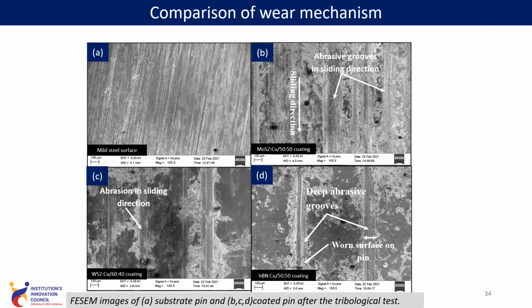This is the comparison of wear mechanism. As you can see, this is a mild steel surface. This is the MoS2 copper surface, WS2 copper surface, and hBN copper coating. In this, it is observed that abrasive grooves are formed. You can see the abrasive sliding direction. This is the surface that showed the lowest wear resistance. This is the surface captured after the tribological test. We can see deep grooves in the hBN copper coating, and also deep grooves in the sliding direction in the MoS2 copper coating, but a low amount of deep grooves in the WS2 copper coating. That also proves that the WS2 copper coating has low wear.